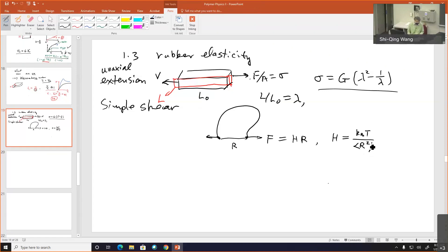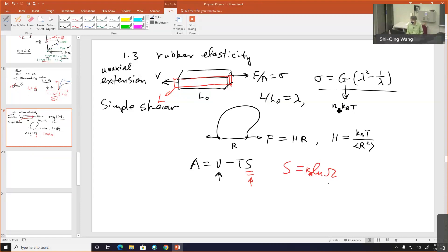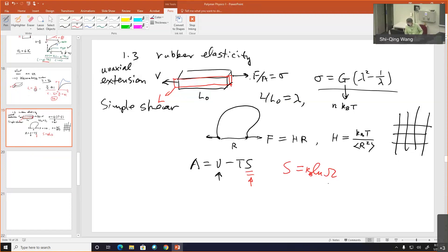You further learned that by considering the entropy change and looking at the Helmholtz free energy — assuming internal energy doesn't change — you compute what the entropy change is according to Boltzmann's principle. That's how you end up with the expression where G is kT times the number of strands, where each segment between crosslinks is a strand.